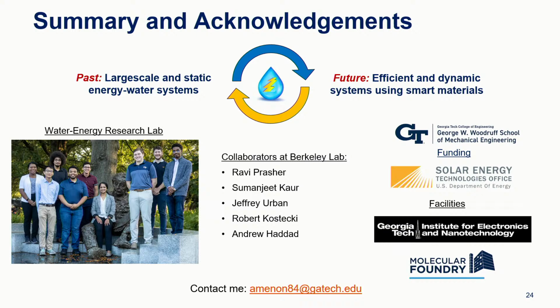So if you operate these structures for more than a few hours, you start seeing the evaporation rate dropping, and then we can look at cross sections of the material and we just see salt precipitated in the pore. So a lot of times the way it's addressed in literature, they run it as a batch process. As soon as they see a lot of precipitation, they will just flow clean water through it to dissolve the salts, and then they will repeat the process.